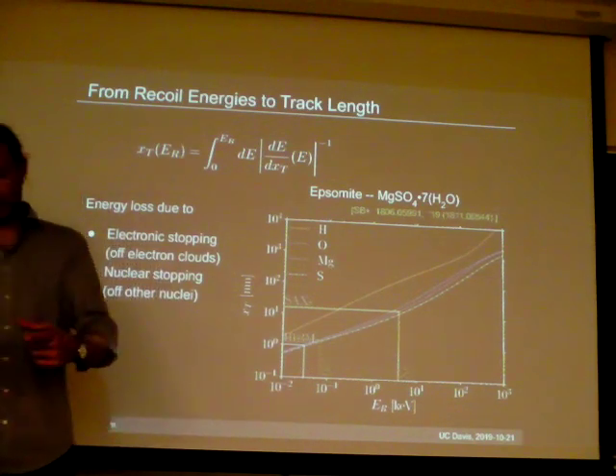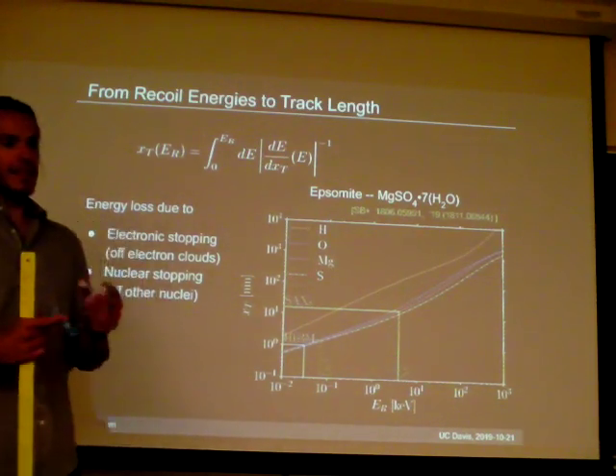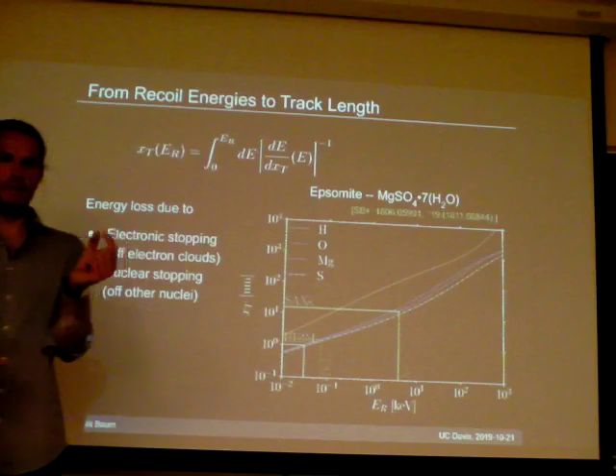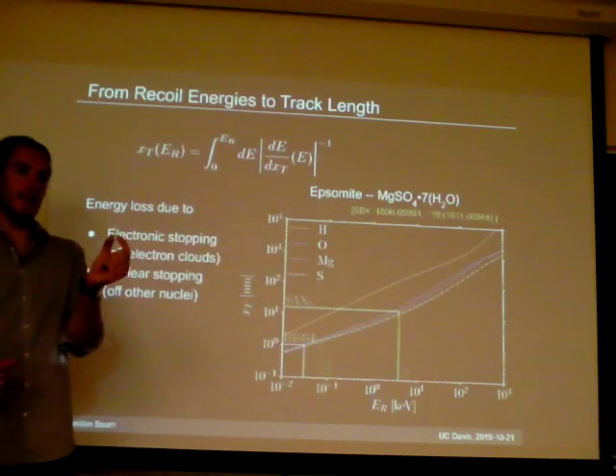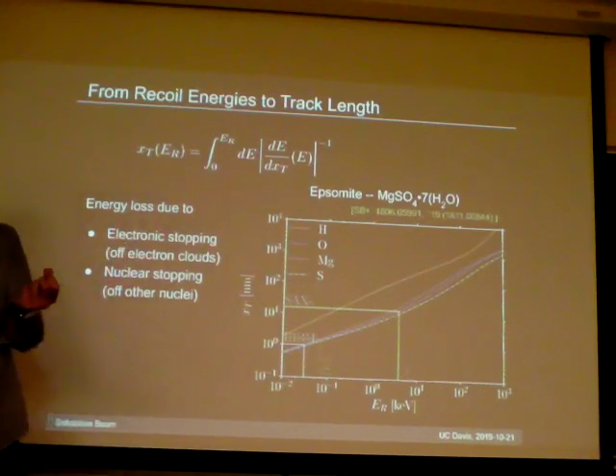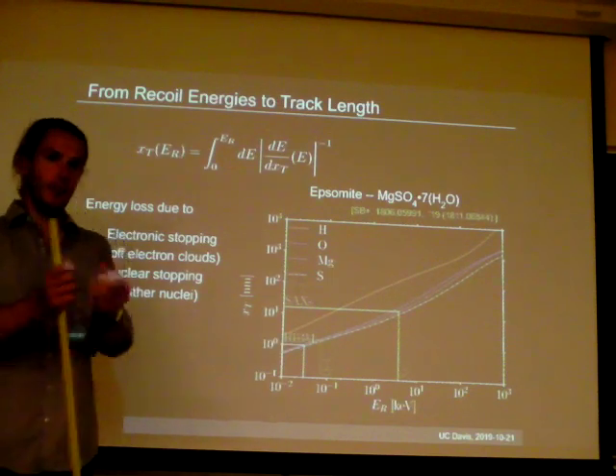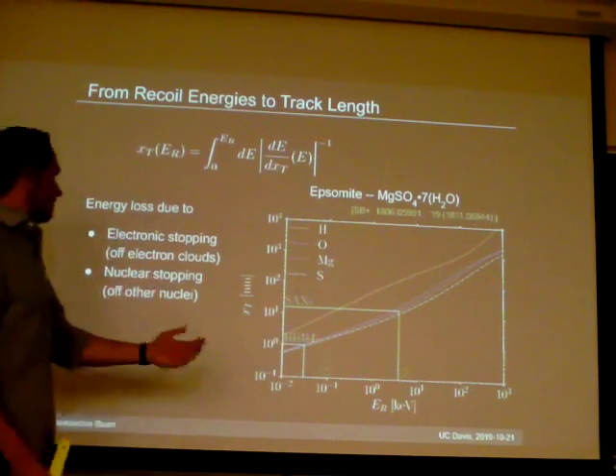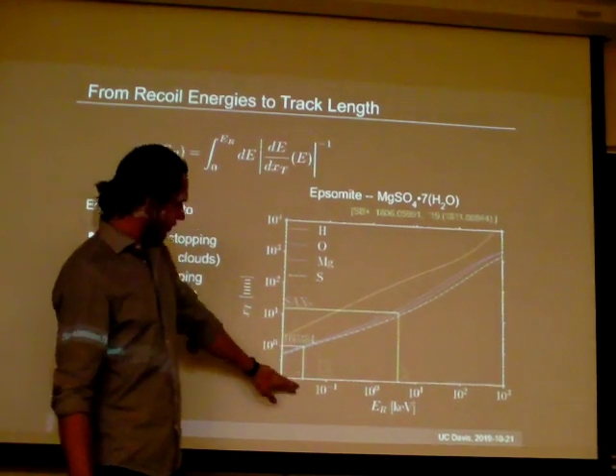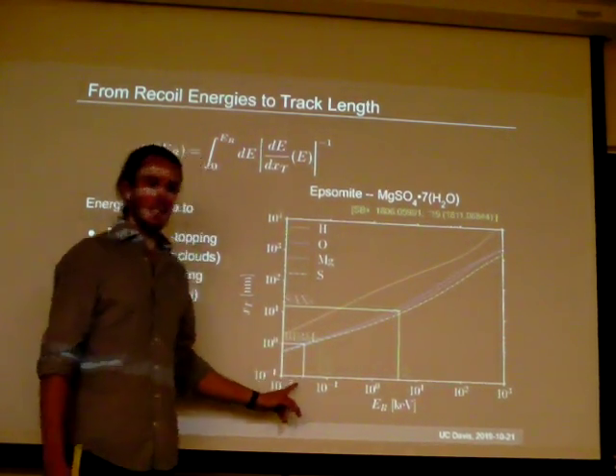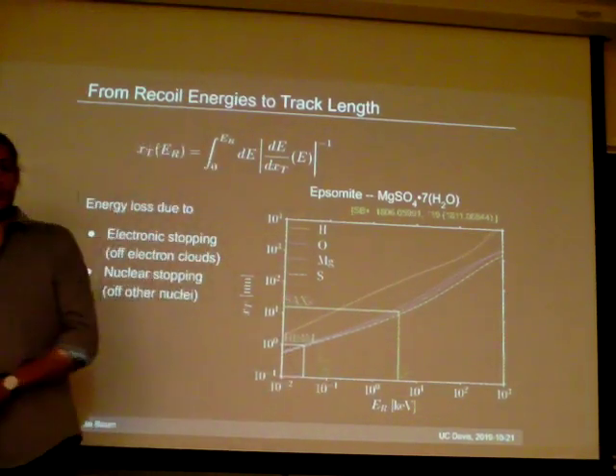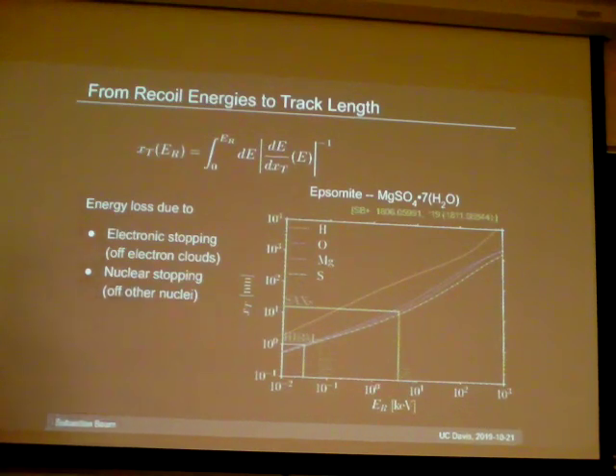But if you think about a lattice in a crystal, the typical distance between the atoms is on the order of a nanometer. So you can't really talk about a track that's shorter than a few lattice spaces at least, right? So let's say we can do a nanometer. Then the energy threshold that corresponds to is a few tens of an eV, right? So if you could do that, that's comparable to what you can do with cryogenic bolometer experiments to look for nuclear recoils.